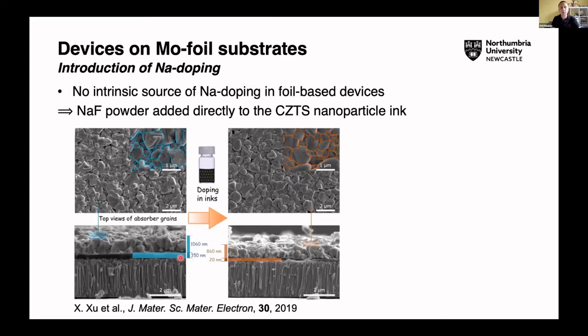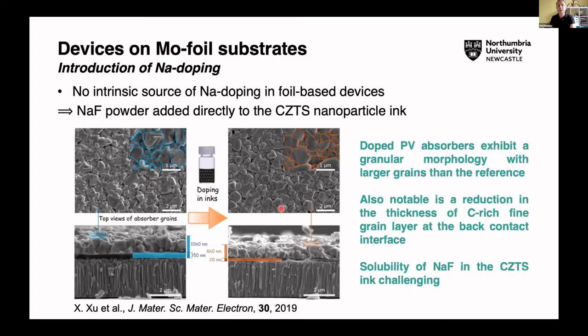And interestingly, one of the characteristics of the nanoparticle ink process is an unconverted or unselenized layer, which is carbon rich at the back of the device, and that carbon comes from the surfactant in the process. And we're able to reduce that a little bit with this doping technique, and also we get a slightly thinner overall layer. So we get some kind of better conversion of the nanoparticles into grains.